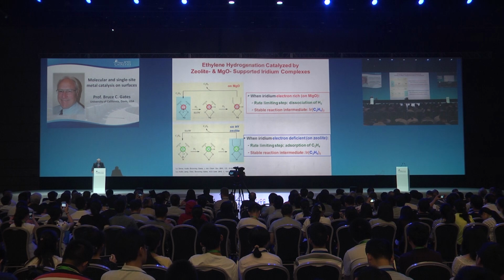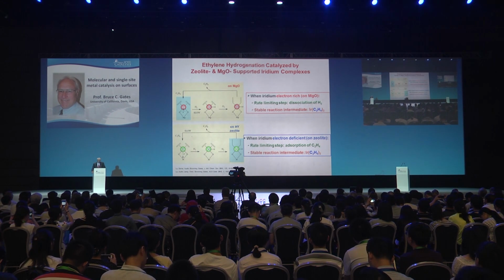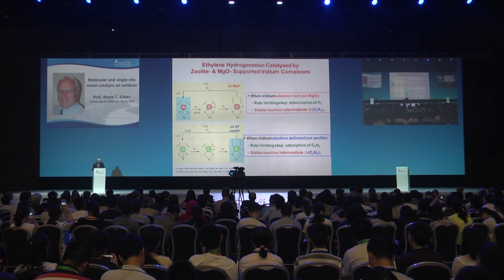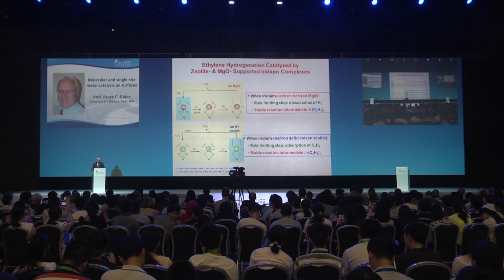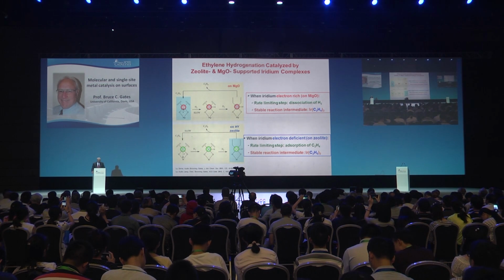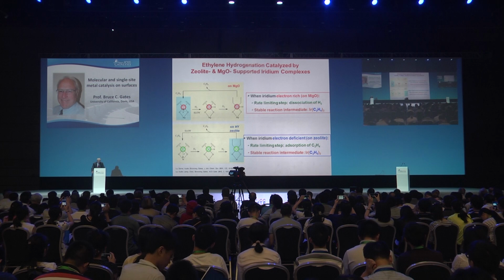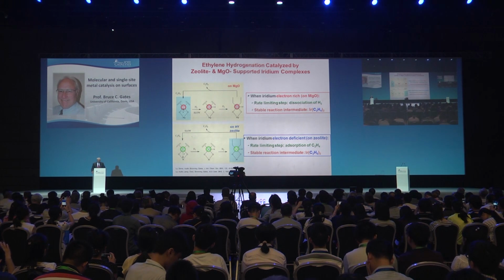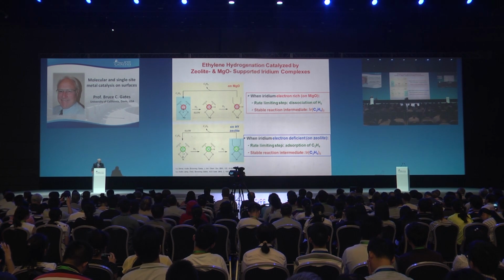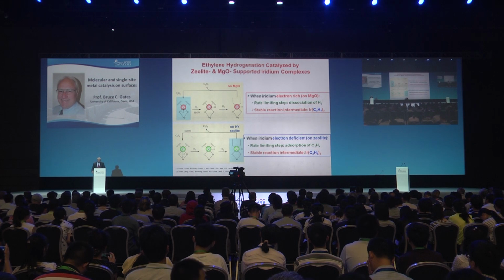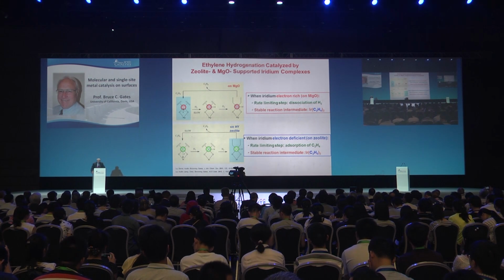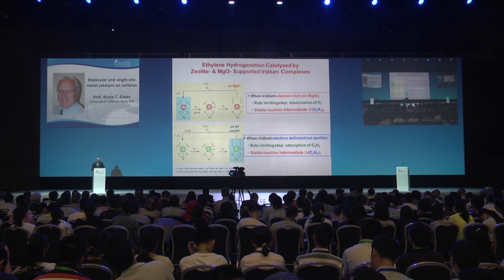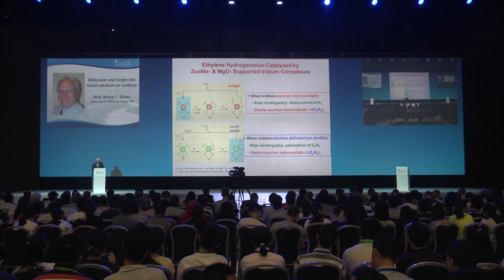This is a comparison of measurements of kinetics and measurements of spectra of the functioning catalyst, olefin hydrogenation on the iridium complex bonded on MgO versus the HY zeolite. And the key point I want to make is that the predominant species in the functioning catalyst is different, one support from another. So the support as a ligand is tuning reactivity.